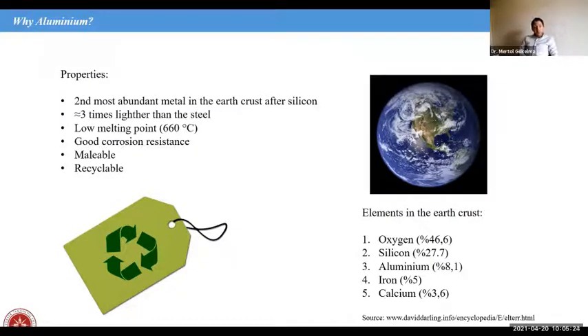It has a good corrosion resistance because aluminium oxide is a very stable oxide. And we can deform it, we can form it. That is why we use it as foils in everyday life. And it is recyclable. Although the oxide of aluminium is not easy to reduce, because it is stable, the oxide percentage in scrap is very low, usually below 1%. And this is not the case for iron. As you would know, you can even see the oxide with the naked eye and it gets bigger and bigger. So you can even completely lose iron because of oxidation, and the same for magnesium, for example. But for aluminium, although we cannot recover the oxide, the metal is somehow protected by that.